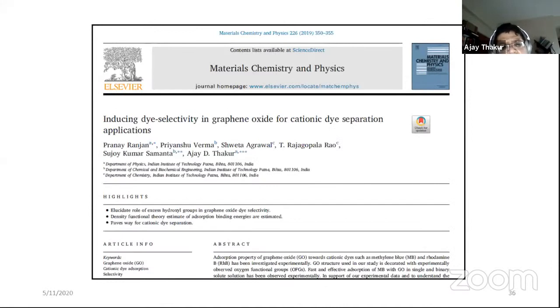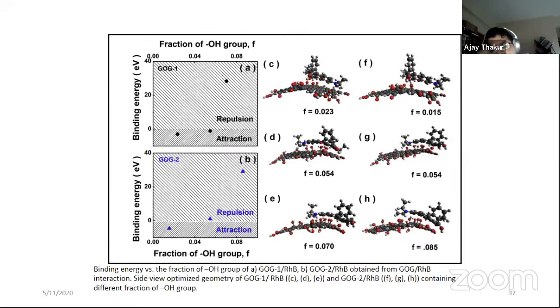Not only that, we also went on to show dye selectivity for adsorption of dyes in graphene oxide via suitable alteration of functional groups. So we played around with the functional groups which are found in graphene oxide, and then we made it dye selective, and we were able to separate two cationic dyes from a cationic dye mixture. So that was something which was a first of its kind experiment.